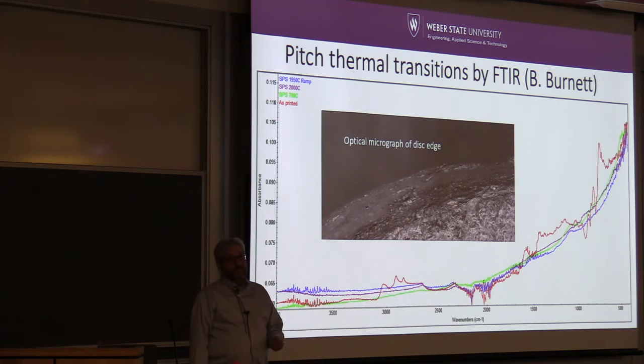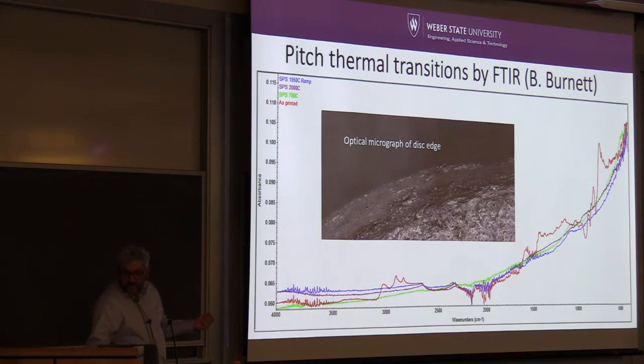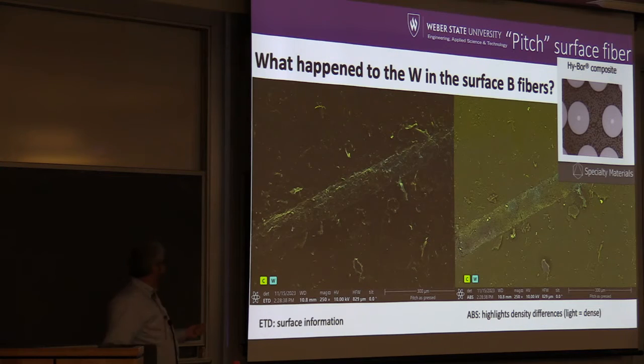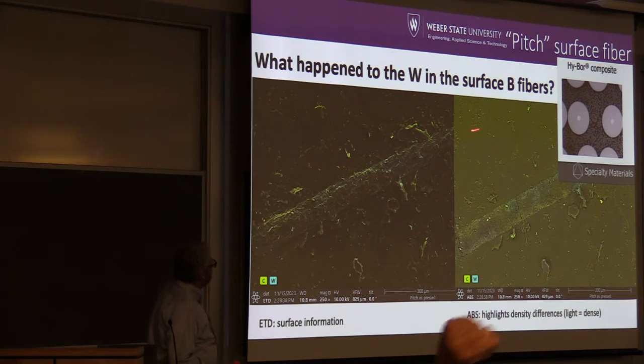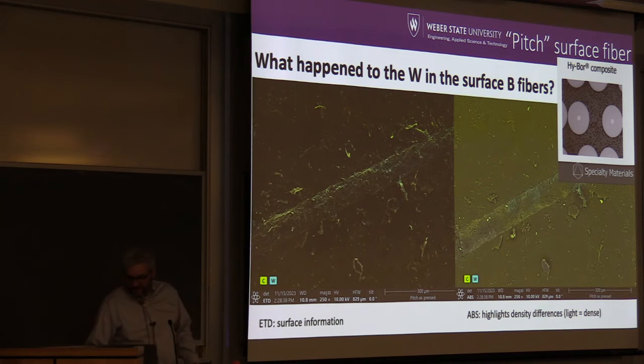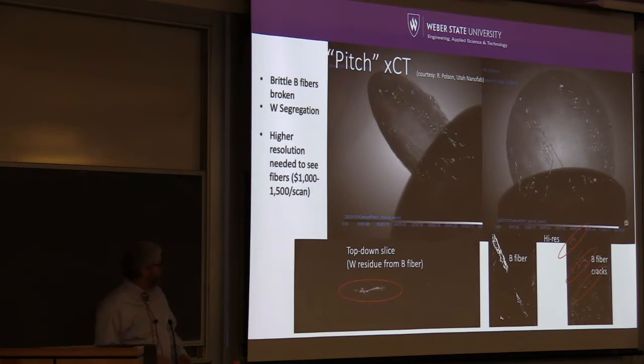That's a terrible mode for FTIR fingerprinting. It's a really good mode for Raman fingerprinting, because Raman loves the symmetry of bonds, and this is where you can pull these things out. I didn't get to do any Raman. That was next on my list. But I started to go, hey, I had these beautiful 100 micron boron fibers, and what happened to them? Oh, here's one, and I should be able to see the tungsten in this image, but everything was busted up and broken and just messy.